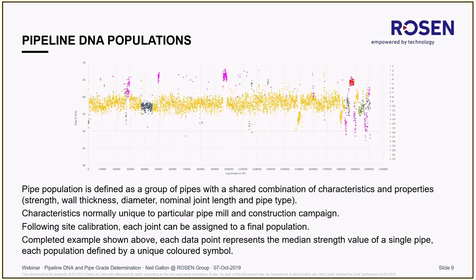This allows you to have a much better informed integrity management strategy, rather than just assuming that all of your pipe is, for example, X52 of 8 millimeters wall thickness. You can go through it and you can work out exactly which different grades it is, where the different wall thicknesses are, where the different pipe mills are. You can then use that to target your integrity management strategy.